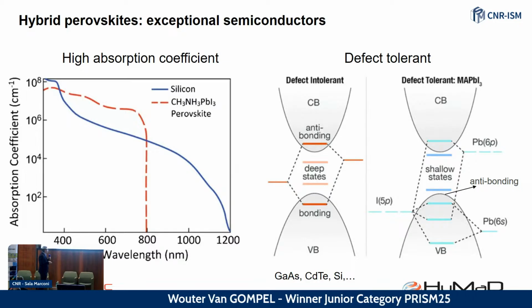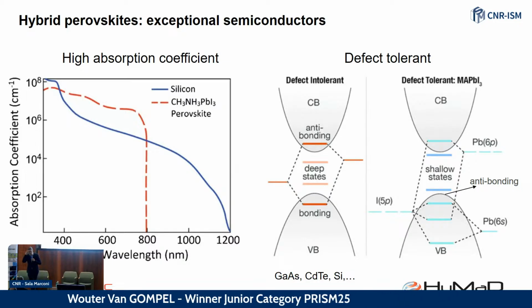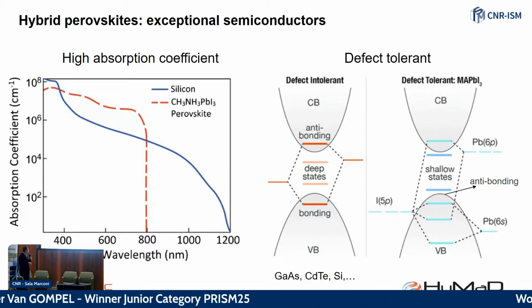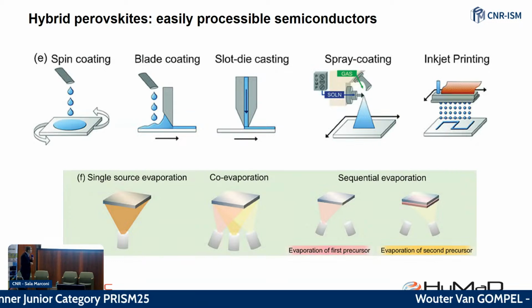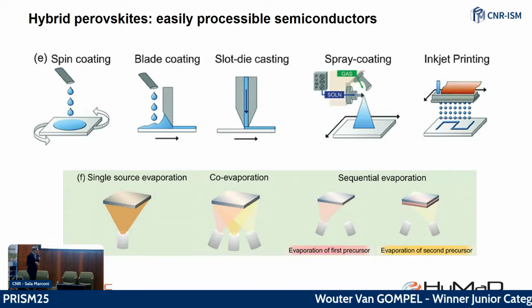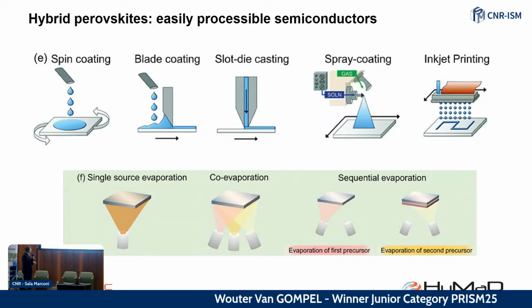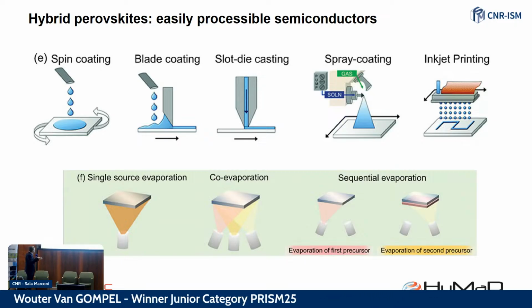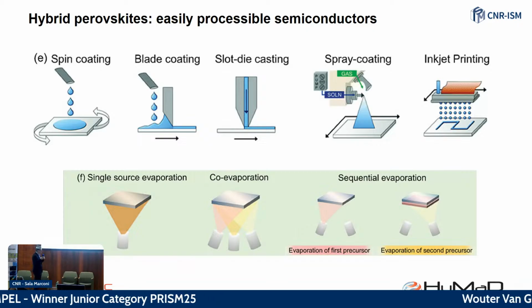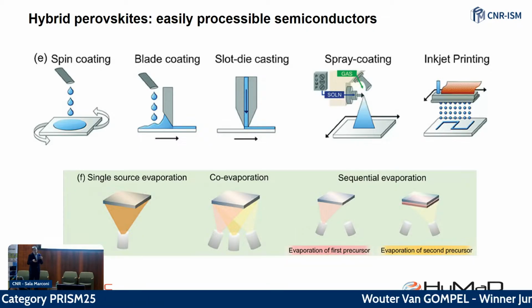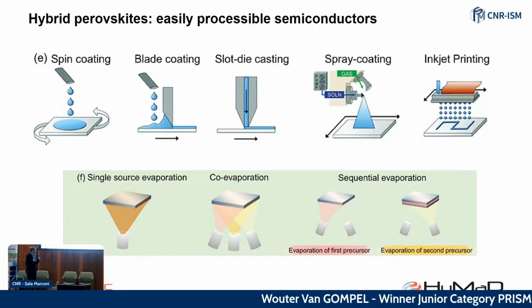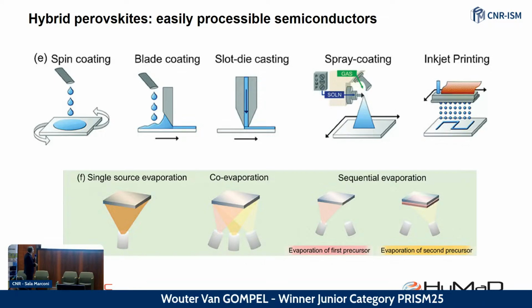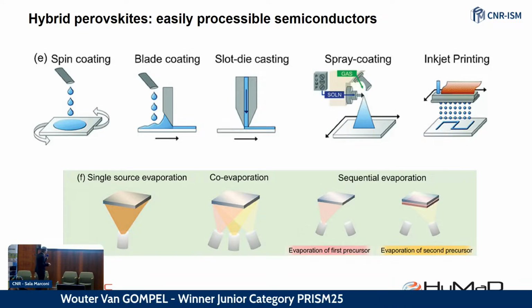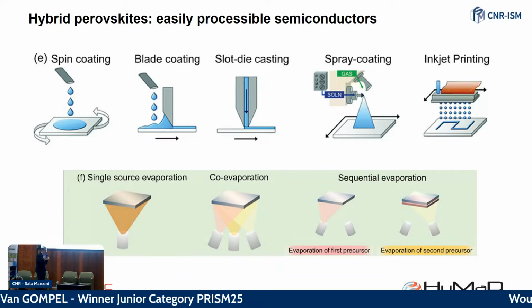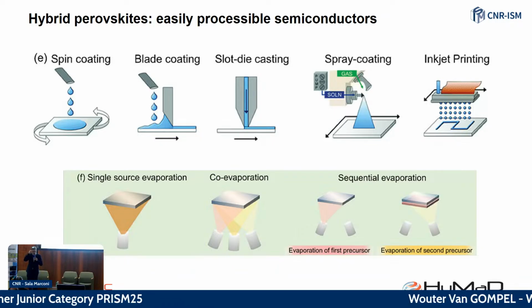But in general, they are quite defect tolerant, which is a very nice property for a semiconductor. So this also means that they can be processed using relatively facile deposition techniques like solution-based spin coating at small scales, but also blade coating, slot die, spray coating, and even printing on the one hand. And on the other hand, they are also generally compatible with vapor deposition, such as single source co-evaporation and so on. So you have quite a variety of deposition methods available for these perovskites.